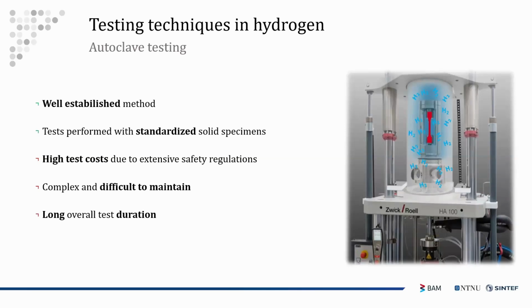Autoclave testing is a well-established testing technique. So it is standardized and we have clear indication regarding the testing condition, but also the geometry of the specimen. On the other side, this technique is very expensive and it involves very high safety regulations because we are handling highly flammable fluid under high pressure. So basically, a hydrogen autoclave is extremely dangerous and should be properly handled by highly specialized personnel. So this technique is very complex and difficult to maintain, and it also has a long overall test duration. So all these limitations reduce the testing capability of a laboratory.